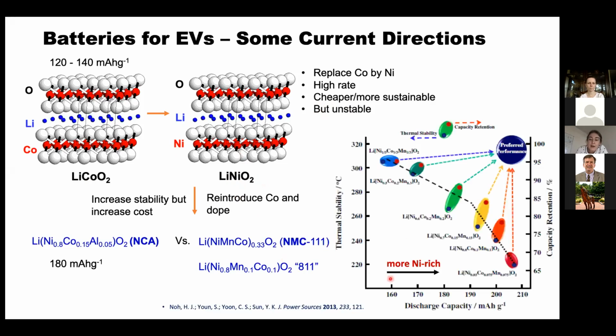And that comes with, as you go to more nickel rich, you have more capacity, but then your capacity retention, so that's the retention as you cycle the battery, diminishes. And so the field is really trying to think about how do we enable these nickel rich materials, but also to get higher energy density, but at the same time improve capacity retention. And I'll come back to that later on in my talk.